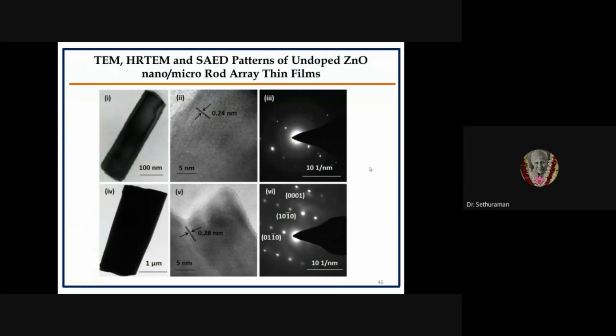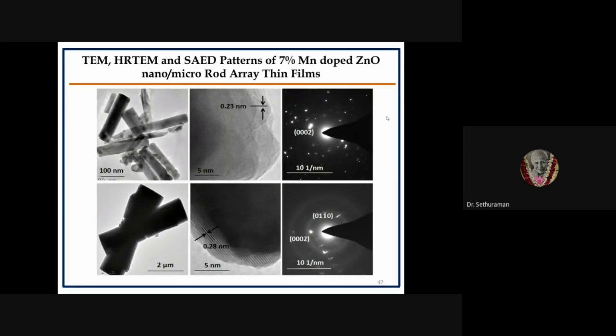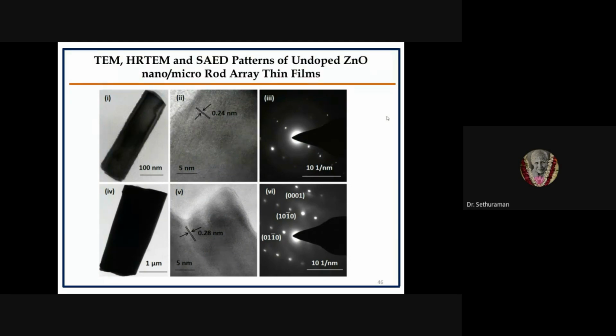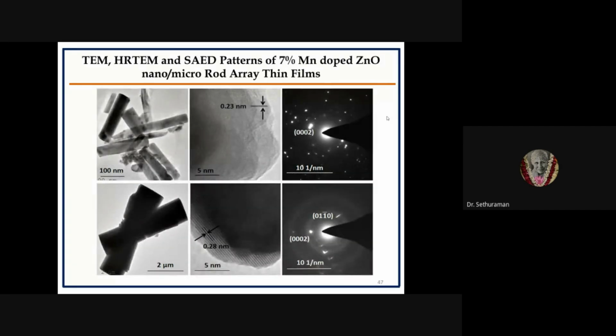Okay. These are the HRTEM and SAED patterns of undoped zinc oxide as well as doped zinc oxide. This one is for the undoped zinc oxide nano micro assembly, and this one is for the 7% Mn doped zinc oxide nano micro assembly. From this we found beautiful standing nanorods on the surface of the 3D zinc oxide substrate, and the orientation also from the SAED pattern. In the 7% Mn doped zinc oxide, the nano micro rods are fused on the surface of the layer of the substrate. You see the 2 micrometer scale, and we found nanorods as well as micro rods on the surface of the glass substrate.